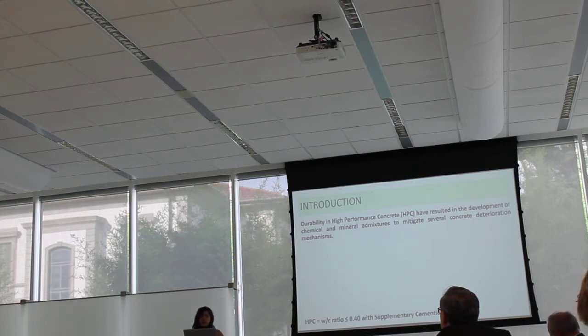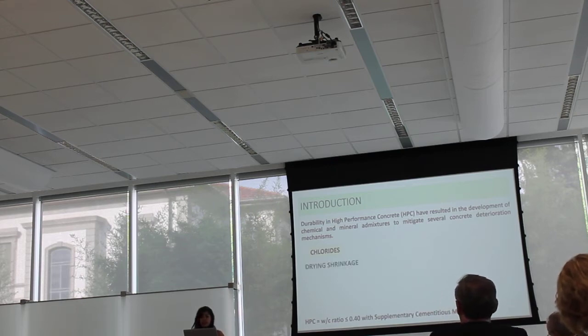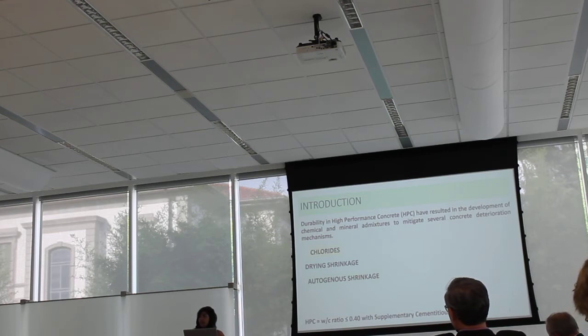Because we are going to have cracking potential. So if we want to mitigate chloride penetration of the concrete, we have to take into account the phenomena that cause cracking potential, like drying shrinkage, which is due to evaporation and loss of water inside the concrete. And we have the worst case, autogenous shrinkage, which appears at early age of the concrete. This is the major problem, because you are going to have cracks maybe at the first day, or the second day, and then even with high amounts of cement, you will have cracks, and chloride can penetrate through them.